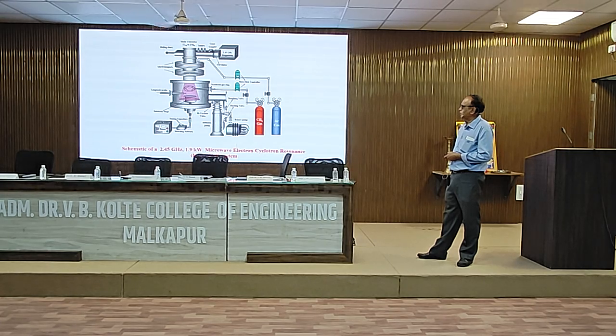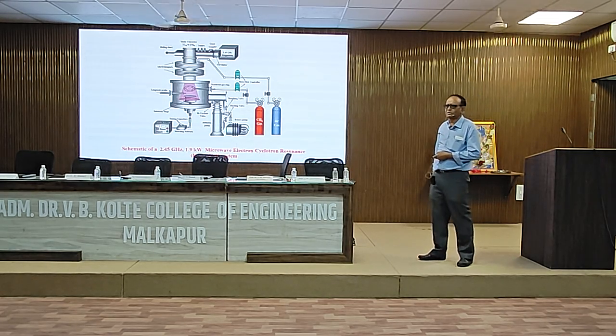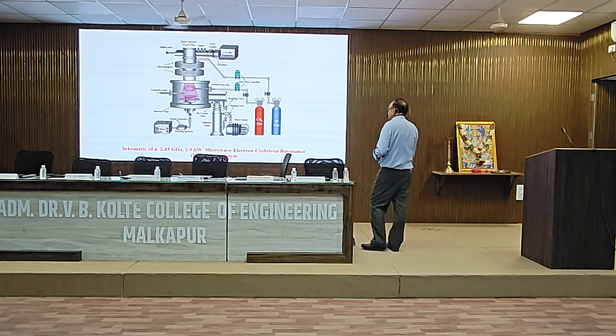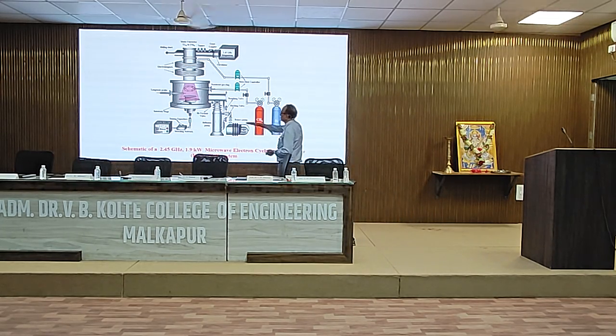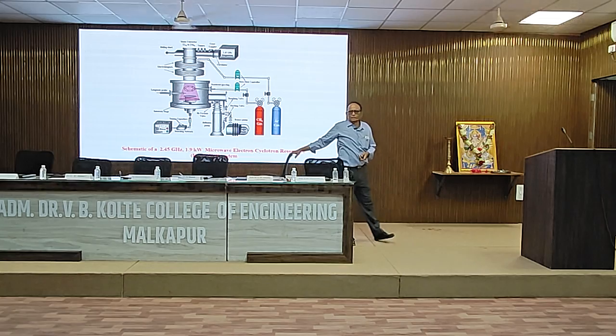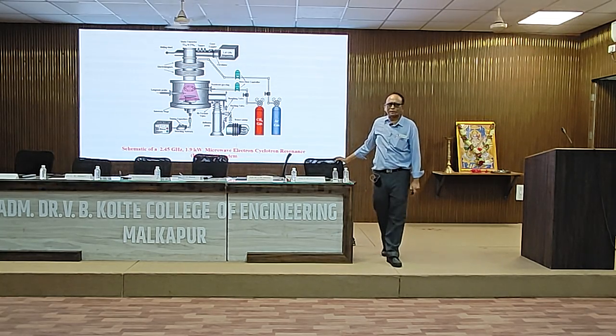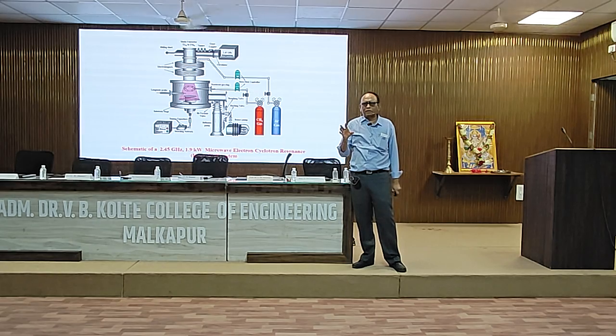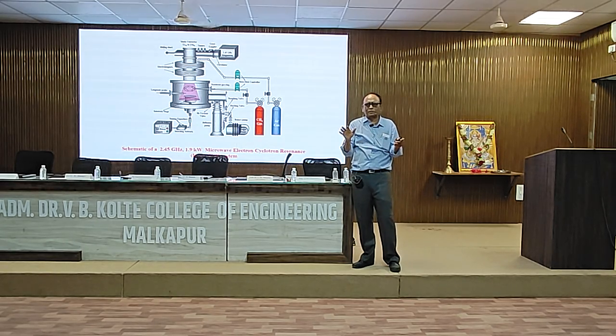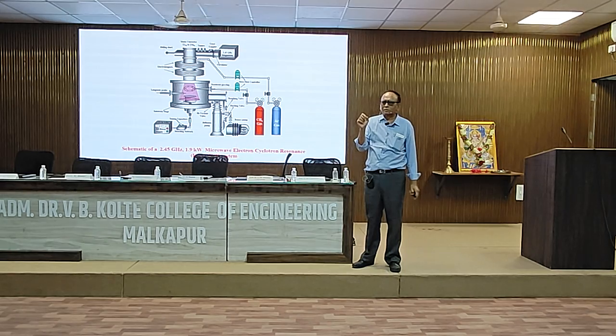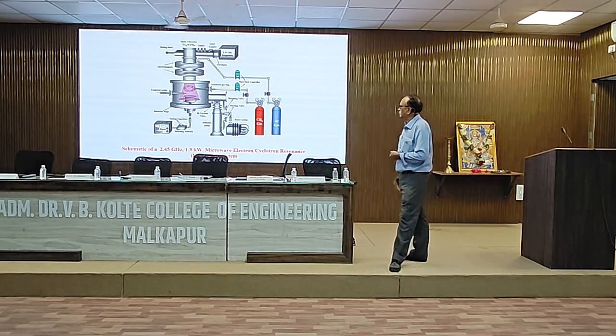Now this is the electron cyclotron resonance system that was made in the year 2000 at BARC, and it generates the plasma in 8-inch diameter. These are your microwave hardware. They are different components brought into the plasma chamber, gas at low pressure. Plasma is generated. Again, these substrates can be biased by RF power, and we use this facility for deposition of diamond-like carbon coating. Diamond-like carbon is nothing but an amorphous phase of carbon which has an sp3 bonded carbon matrix in the amorphous phase, and in which there are sp2 bonded graphitic clusters, and that has a very large number.